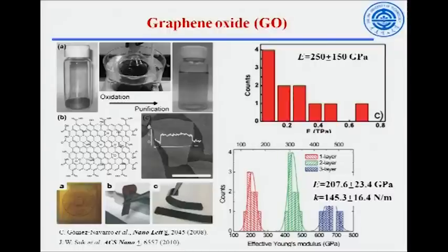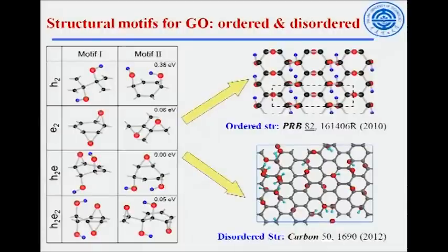The second part is the mechanical property of graphene oxide. Graphene oxide is a counterpart of pristine graphene and can be very easily made by oxidation of graphite. It is also a much cheaper way to achieve graphene-related materials. The mechanical property of graphene oxide has been measured in two experiments, and it was found that the Young's modulus and the elastic constant are lower than pristine graphene. In our previous work, we proposed a structural model, in particular this structural motif for graphene oxide. Then we can assemble this zero-dimensional localized motif into ordered or disordered structures under 2-dimensional periodic boundary conditions. So we proposed two kinds of structural model for graphene oxide.